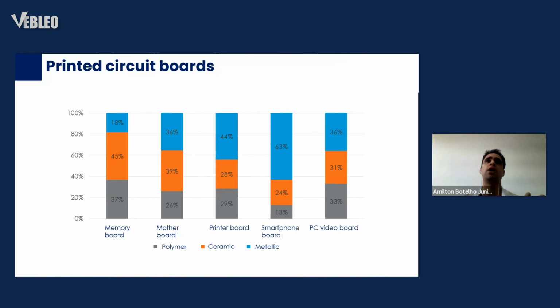And the main reason we have to pay attention to the metallic fraction is that the main compound is copper. Copper is the main element in PCBs and in the metallic fraction. Its content is much higher than in the primary source. We have at least 1% of copper in the ores found in nature. In your smartphone, we can find at least 10 or 20% of copper in the whole PCB.